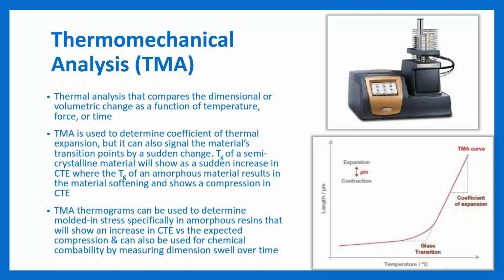TMA can also be used to determine molded in stress, specifically in your amorphous materials. So instead of showing that compression after the TG, it'll actually show an increase in your CTE right nearing your TG. And so as you know the TG of, if we're using the ABS as the example again, as it's nearing the TG of that, you're going to see a spike versus a drop off that you would expect because of the ABS material.